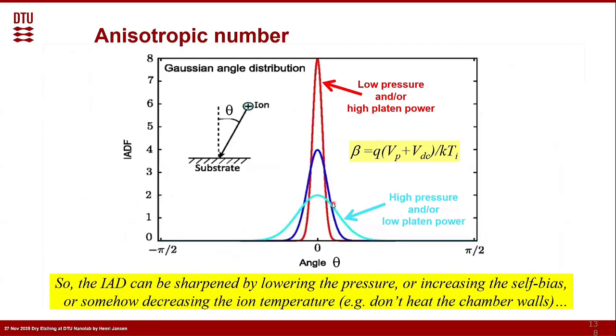So now, if I want to make a structure where I would like to have the ions striking the surface as straight as possible, we don't want an ion angular distribution with a full width half maximum of, let's say, 40 degrees. It would really start to bow or bottle my structures. It would not be straight. I would like to have a few degrees or so. If we etch it and say, oh, it's not good enough, we can sharpen it. We know now that by lowering the pressure, the plasma potential goes up. We know that one.